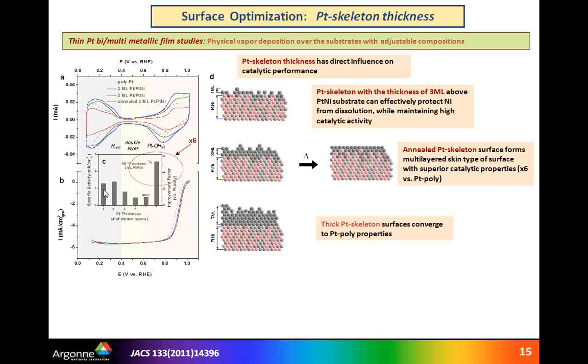And one can see that once we started to deposit several monolayers, going from 1 to 3 all the way to 7, specific activity started to drop. And the specific activity of the surface which had 7 monolayers of platinum was very much the same as polycrystalline platinum. So again, we were able to establish a sweet spot in terms of the thickness of the remaining platinum skeleton, and that was found to be 3. So 3 layers of platinum skeleton is thick enough to prevent further dissolution of nickel, but also it is thin enough to still provide that beneficial effect of subsurface nickel.